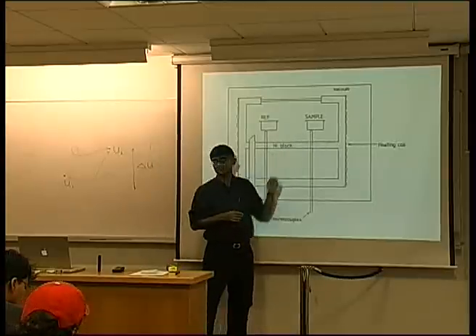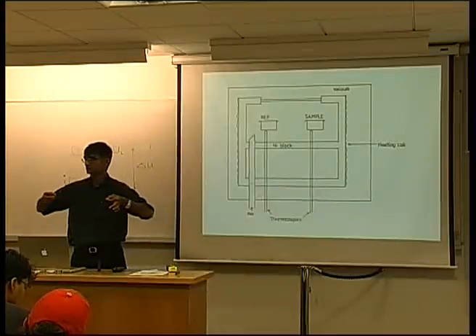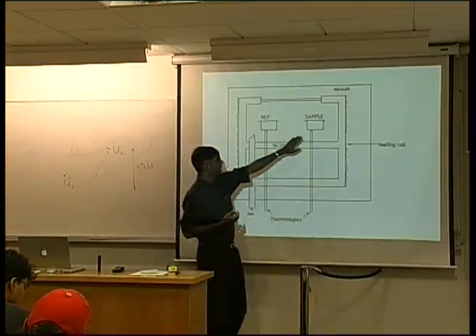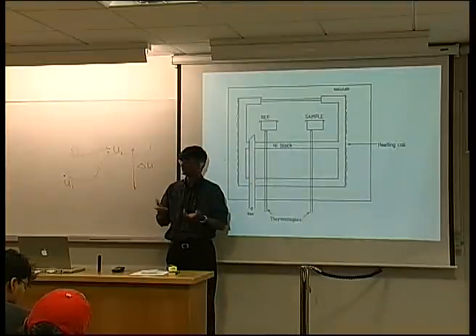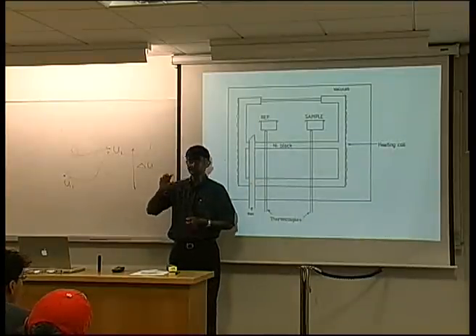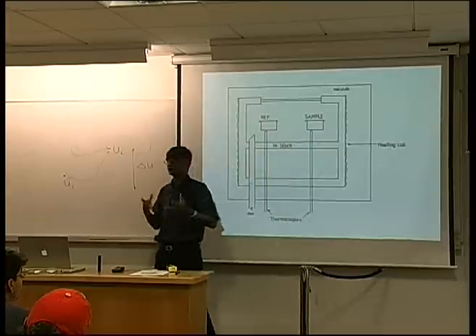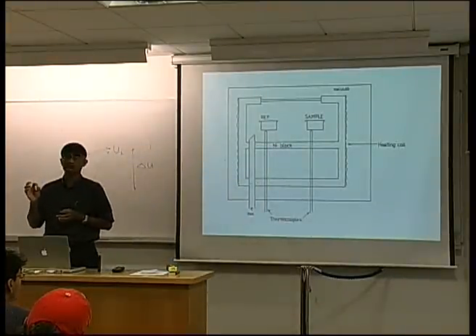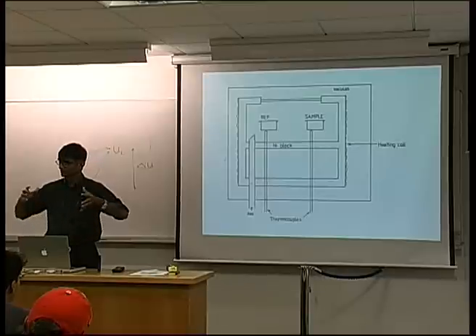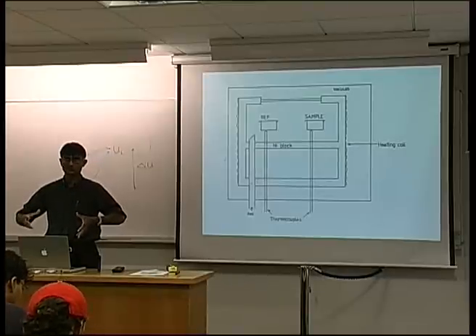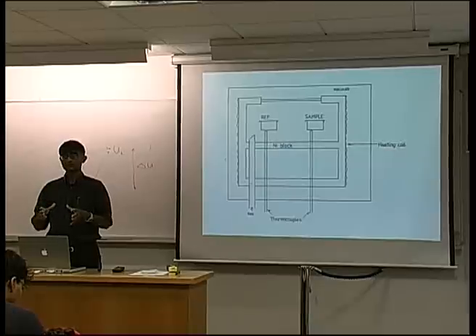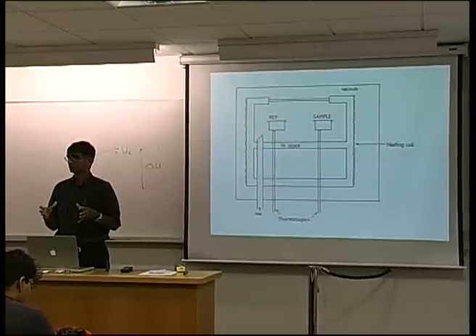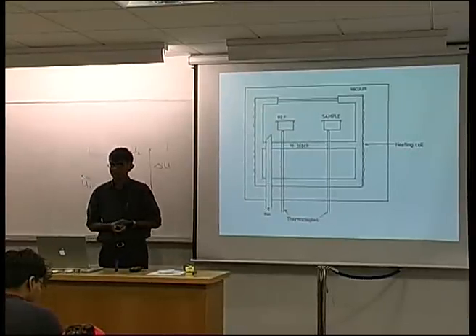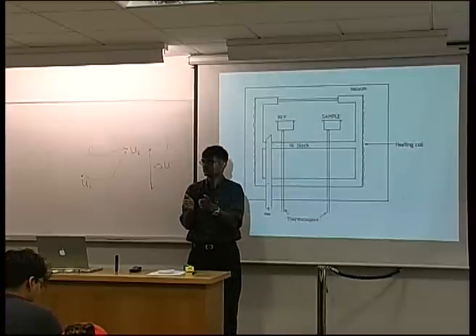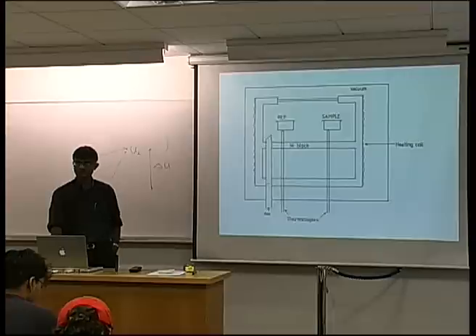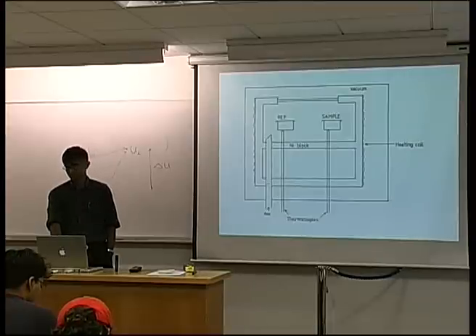You then put your sample in here, and you heat both the containers at a constant rate. And of course, if this is absorbing energy relative to this, then its temperature will be different. So from that temperature difference between the sample and reference, you can calculate the heat capacity on milligrams of material. You no longer need to do large samples as we used to do in the old days. And you can imagine it takes a long time for a large sample to reach equilibrium, whereas a small sample can reach it rapidly. And the whole of this thing would be actually quite small. So it's very easy to measure the heat capacity of materials.